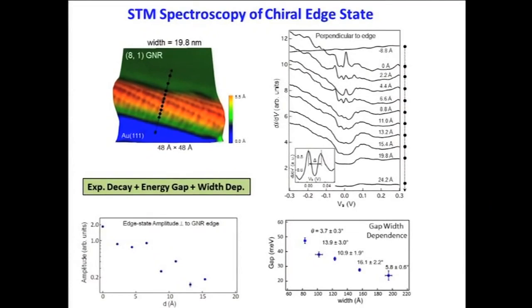First, I want to point out that we do not know what is the actual termination. You know everything that I know, because everything I know is right here on this slide. STM too. So this is our edge. So we definitely know the chirality of the edge because we know this structure. But the actual termination, like is it terminated by a hydrogen atom or a carboxylic acid or an oxygen atom, that we don't know. So we don't know the absolute edge termination.